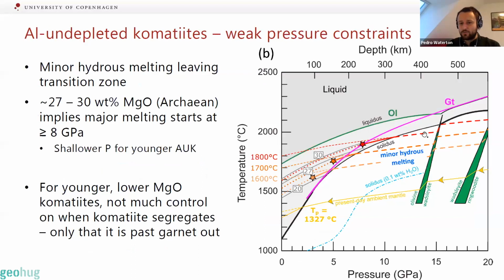And so melting effectively ceases at the garnet out curve. So for these high temperature, high pressure ones, we can be fairly sure that when they start melting, they cross the solidus and then they basically stop melting at garnet out. And for the younger, lower temperature, lower pressure ones, they might continue melting past this point. We're not quite sure.